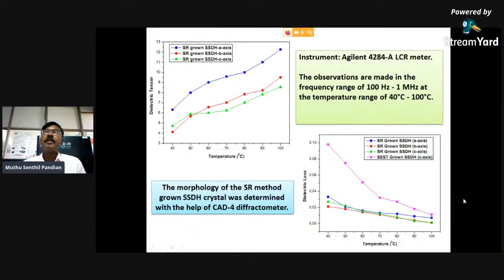Because of the higher optical quality, higher optical homogeneity, higher mechanical stability, and higher crystalline perfection, the dielectric loss value for the SR grown crystal is lower compared to the conventional method grown crystal.